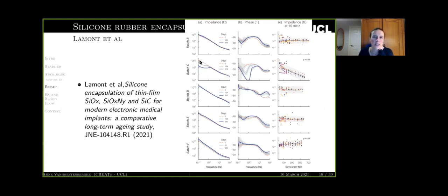And we started detecting, after a period of time, a change in the magnitude of the impedance spectrum, and a change in the phase of the impedance spectrum. So you need extremely sensitive equipment to detect this. This is not a functional failure.